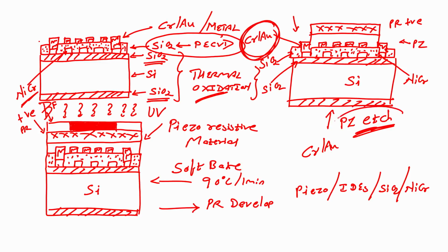Why? Because the chemicals that are used to etch the piezoresistive material will start affecting chrome gold, because the chemicals are such that they can also etch chrome gold. In this case, what will happen? The chrome gold here and here, right, will be etched. If that is the case, we will lose the contact to the interdigitated electrodes, correct. Then what is the purpose of fabricating interdigitated electrodes?